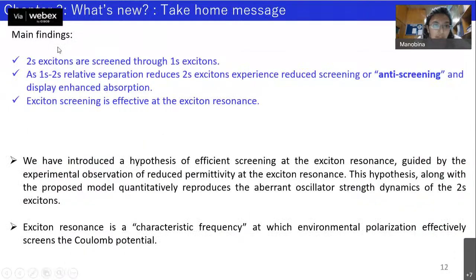So now the main finding from this study is that these 2S excitons are screened via the 1S excitons, and mainly this exciton screening is effective at the excitonic resonance. So here we introduce the hypothesis that efficient screening at exciton resonance, and from our experimental data it matches, and we say that excitonic resonance is a characteristic frequency at which environmental polarization effectively screens the Coulomb potential. So this is our first ever experimental demonstration of the dynamic screening.